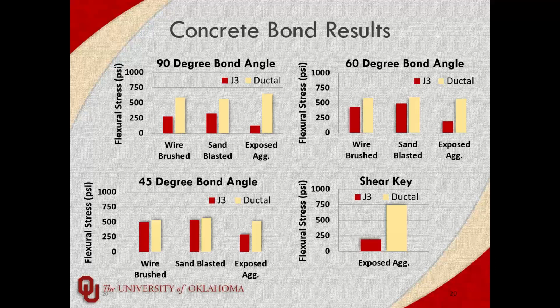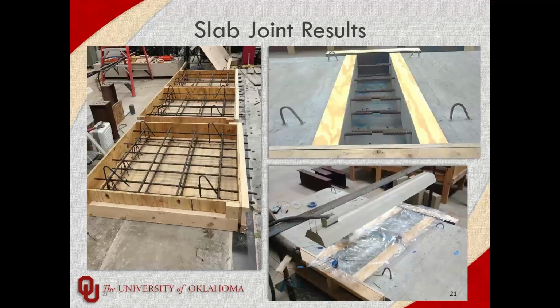All right, and lastly, before we go on, did you use any defoamer, and did you measure fresh air content? Did you say defoamer? Yeah. No, that's mainly the reason I believe that we didn't have the bubbles rising to the surface. We avoided using that just for cost, but we didn't do air content. Although that would have been a good number to have to compare to Ductal, because we obviously would have a much more porous structure than Ductal would have.